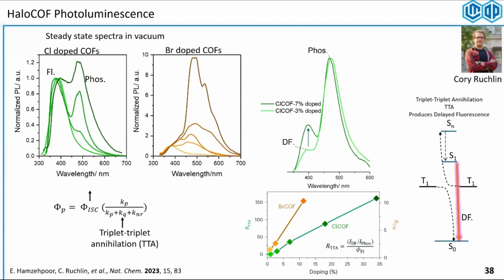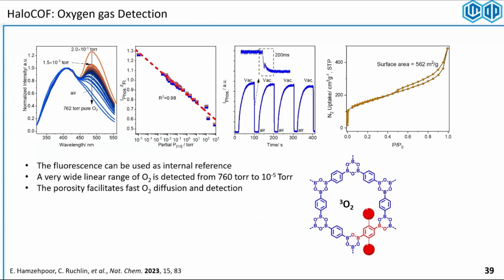It's not a nanosecond regime anymore. It's really milliseconds to microseconds. And if we map this delayed fluorescence ratio to the phosphorescence peak for a particular intensity of light that we were using for the COF, we found a nice, almost linear correlation with the doping. The more you dope, the more delayed fluorescence you have, which is an indirect way to say that more triplet annihilation was occurring. So it's really a game of balance in such systems.